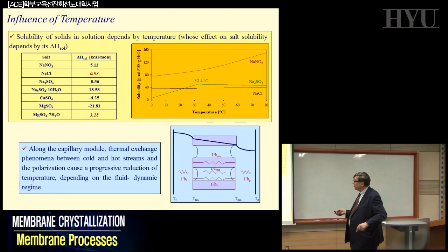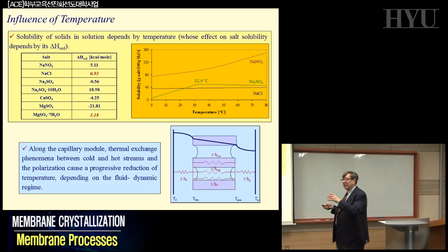I will mention that you must be careful, for example, about the solubility. The solubility is a function of temperature. So depending on which range you are working in, you can induce or reduce the probability of precipitating different compounds together. You can have different forms of sodium nitrate, sodium sulfate, sodium chloride. Each one has a typical behavior in terms of solubility as a function of temperature. And that can be a parameter you can use positively, that means if you know and you understand, you can separate in different forms, or negatively, if you don't realize this and you precipitate something that you don't want to precipitate, and during precipitation you can have a different problem.